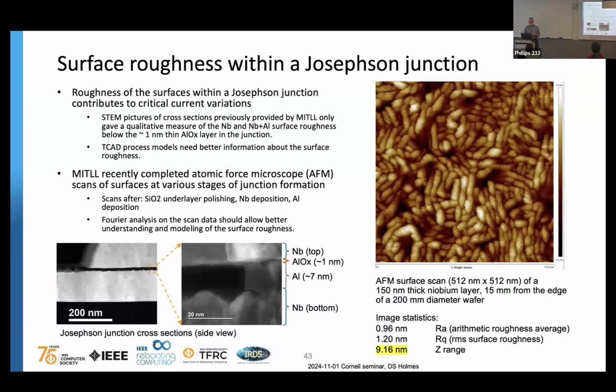This is an example of surface roughness. We've scanned the surface roughness, and I'll just make the comment. This is the surface of the niobium, and if you run these statistics, you get some numbers like the RMS surface roughness is 1.2 nanometers. Well, maybe that doesn't sound so bad, but if you look at the range, 9 nanometers, and then you look at the picture and you say, okay, here's a high spot, and then there's a low spot, and they're pretty close together. You get a sense for, there's some serious variation here that looking at RMS numbers really hides, okay?